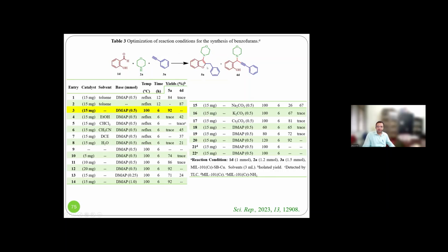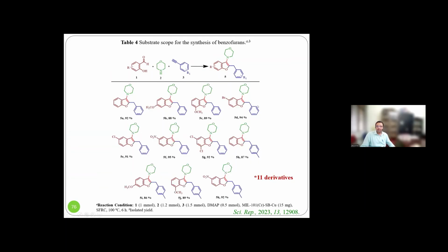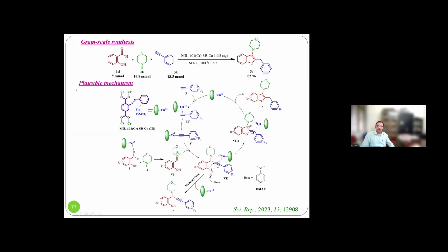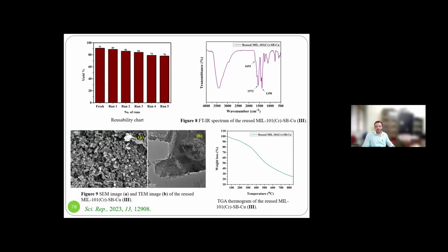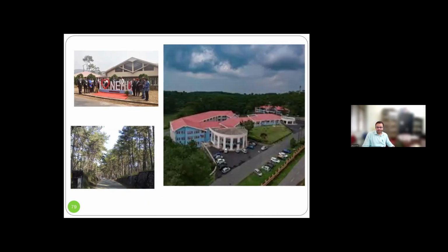Benzofuran is formed. Here we prepared 11 benzofuran derivatives. Now for the mechanistic study, we propose that first copper insertion, then addition of the Schiff base, then addition here in the imine bond, and then intramolecular cyclization gives the propargylamine or benzofuran. Reusability we examined, and the reusable catalyst, we examined the morphology of the reused catalyst.